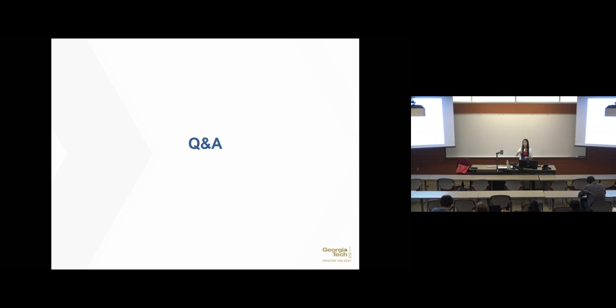That's a very good question. That's actually related to the previous question about the size, right? In order for everything here to work, we have to probe the material at the continuum length scale. The network size of the material, the molecular length scale you worry about, is about a few nanometers to 10 nanometers at most. And the contact radius we probe is a few micron. So we certainly are probing the material at the continuum level. We use AFM in a non-conventional way, not mapping this very small length scale. We don't use a sharp tip.